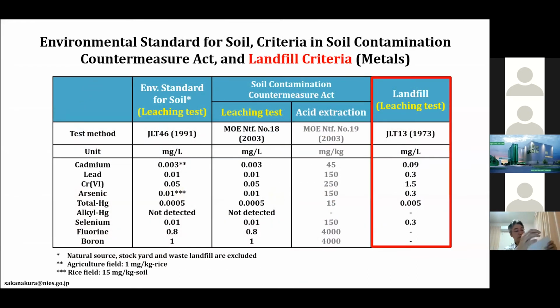This slide shows the environmental standard for soil and criteria in the Soil Contamination Countermeasure Act and the landfill criteria. Although the names of the test methods are different, the procedure is very similar among the three leaching tests. So we can compare and say the landfill criteria is 30 times more relaxed than the soil environmental standard. However, untreated fly ash cannot satisfy the landfill criteria, especially for lead.